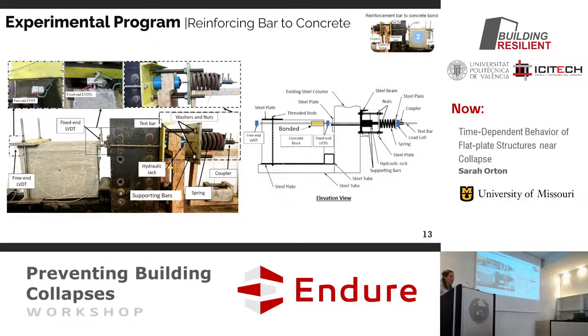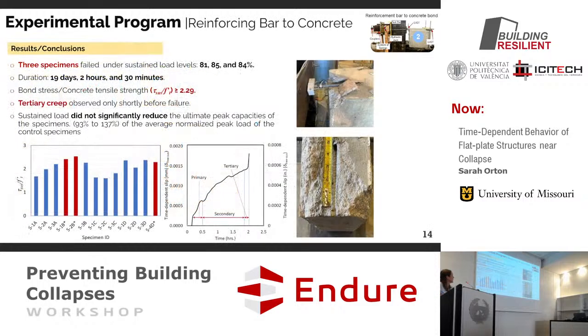I pulled on it, left it under sustained load for an amount of time, and we had 3 specimens fail under sustained load at load levels of 81, 85, and 84% of their capacity at 19 days, 2 hours, and the one at 30 minutes. One didn't last very long.